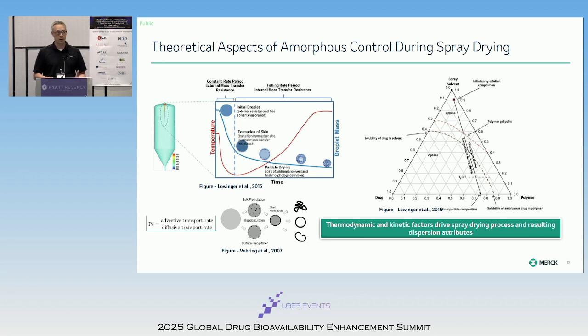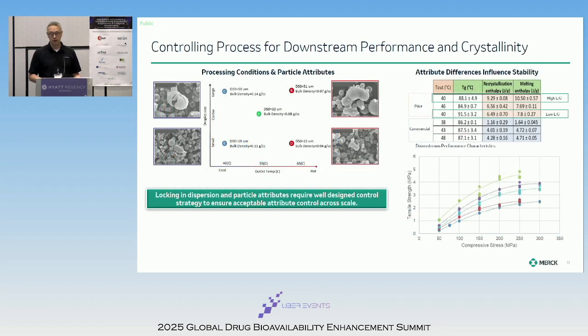If you characterize with techniques like XPS, you can actually see heterogeneity within an individual particle. You also get a complex microstructure where, depending on the rate of drying, you can get spherical particles, you can get raisin-like particles. If you were to cross-section them, you can actually see internal structure there as well. So a highly complex process that needs to be very well controlled.